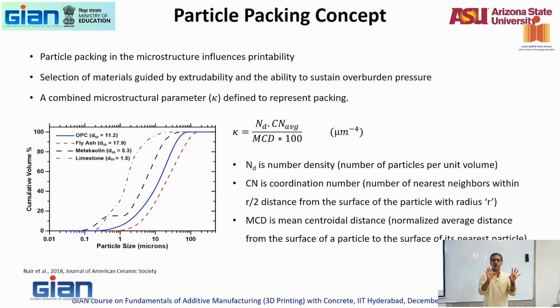Hexagonal close packing or face-centered cube both have an atomic packing ratio of 0.74, which means if I take a box and take same size spheres and I pack them in the form of a hexagonal close packing or a face-centered cube, I can pack 74% of the volume of the cube with these particles. The remaining 26% will be empty. So if I have only spherical particles, which is what we will do to idealize, like you've seen in the morning, what do I need to increase my packing fraction? I need to add smaller particles. If you keep on adding smaller and smaller and smaller particles, you can get to 0.905. That is a theoretical absolute maximum particle volume fraction that you can get.